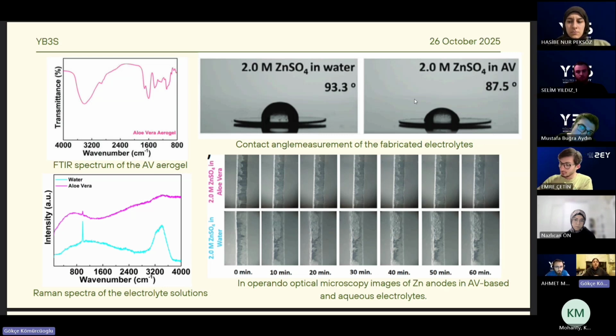Also, by the Raman spectra, in the comparison with aqueous electrolyte, they saw that the electrolyte inhibits the free water molecules and enhances the stability. With the holding of the free water molecules, it reduces the hydrogen evolution reaction.